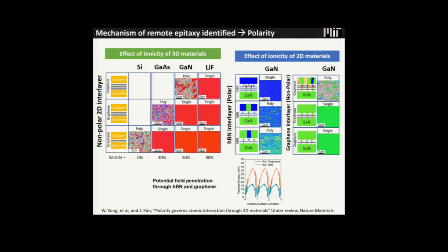There are mixed orientations here. Some are seeded from HBN, some are seeded from gallium nitride. If you increase the layers, the gallium nitride remote epitaxial seeding effect is disappearing. Then if HBN is three layers, there's no remote epitaxial effect anymore. It's just seeded from the boron nitride. So the polarity of the 3D material and 2D material does matter for determining whether you can have remote epitaxy or not. That's what we found.